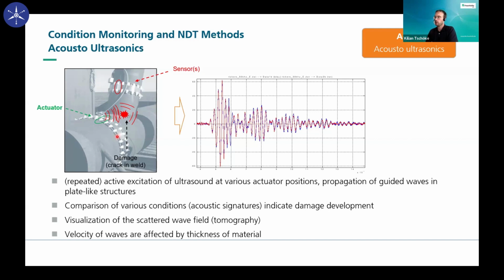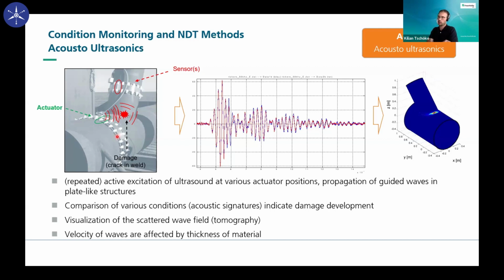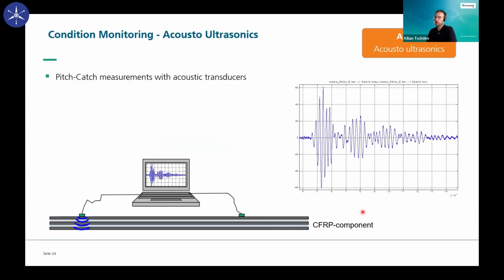By analyzing all these signals, and here you can see we have 2 sensor belts with a lot of different transducers. By using all of this information and more detailed signal processing, you can get really detailed information about damage positions. In this example, it was an artificial crack, a cut into the welding of this metal pipeline structure. This technique also works for composites.